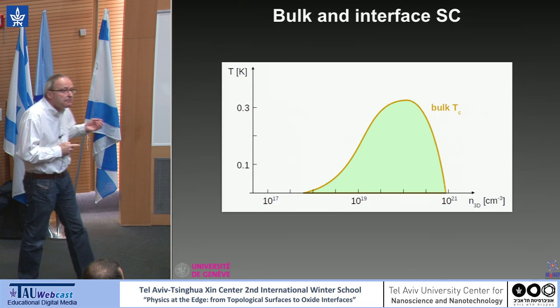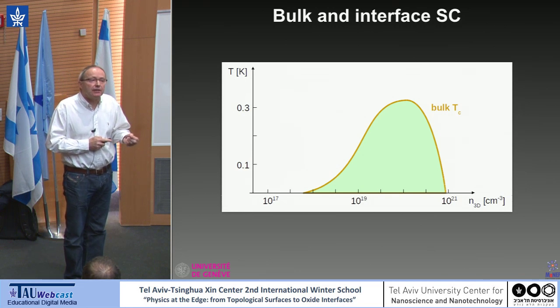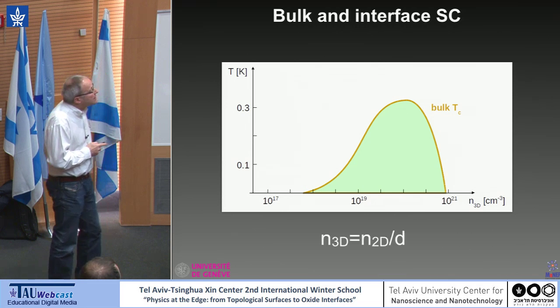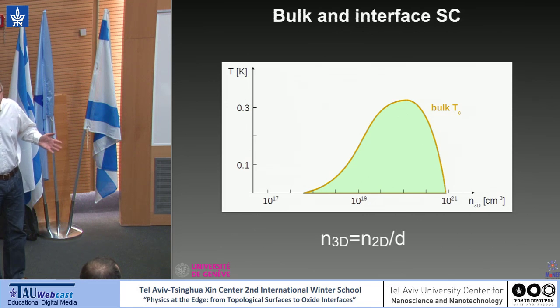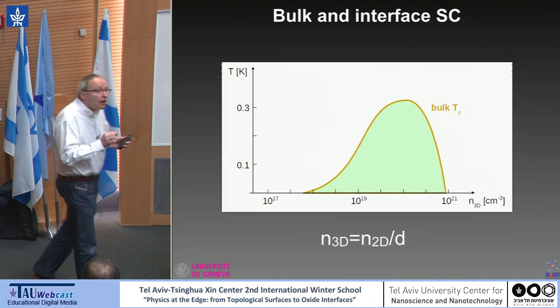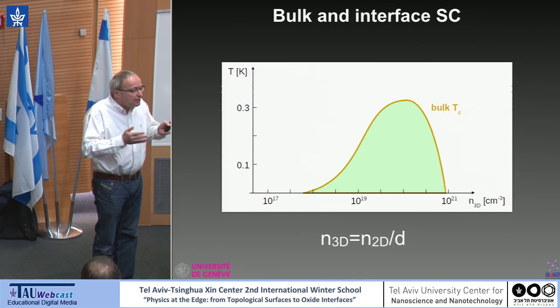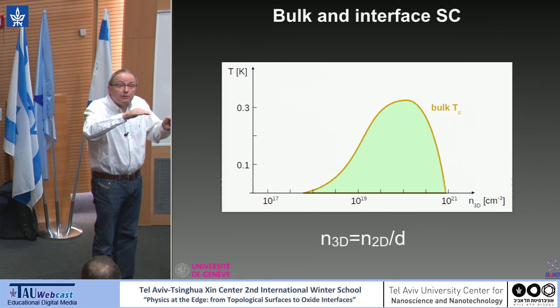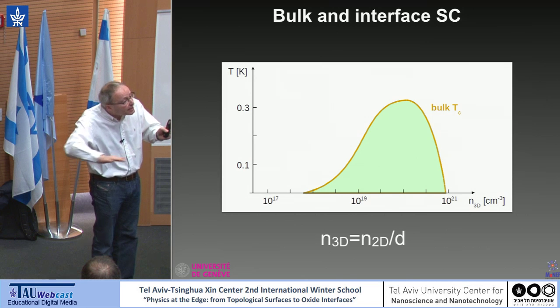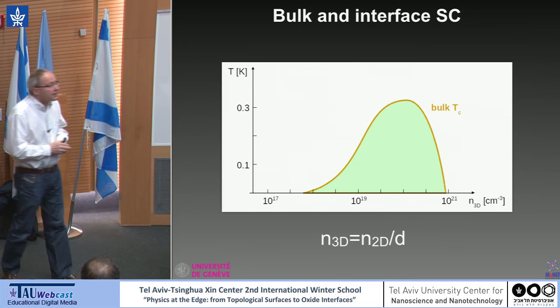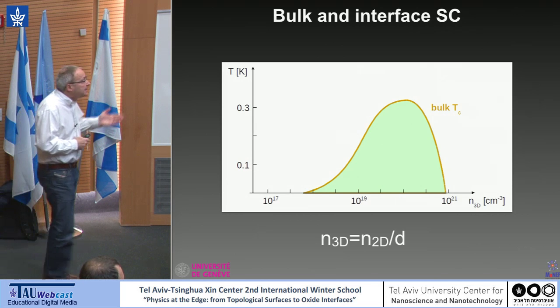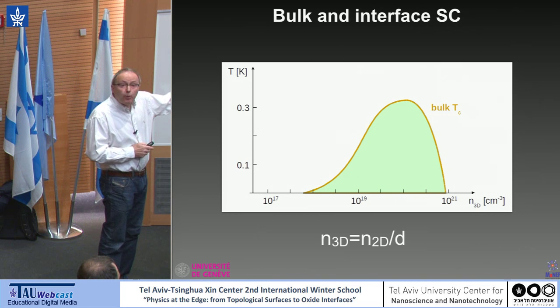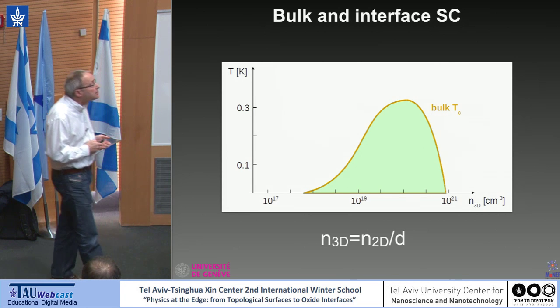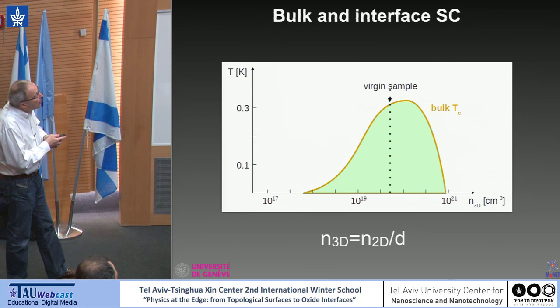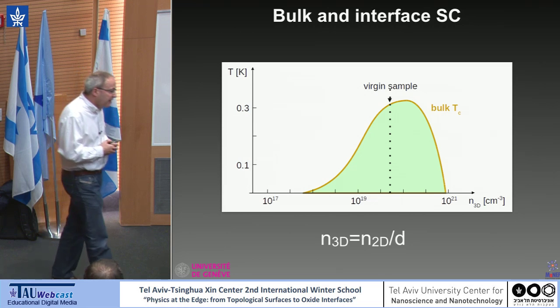The first thing to do is to translate the sheet carrier density we have to a 3D carrier density. In principle, it's very simple: you just have to divide by the thickness. Maybe a first thing to notice, and possibly a problem, is that in our system the carrier density is not homogeneous. We have some kind of an exponential decay when you move away from the interface. But as a first step, let's simply divide our N2D by D and see where we are in the phase diagram. For the maximum TC, we find that our volume carrier density is here, and so we are reasonably well placed in the phase diagram.